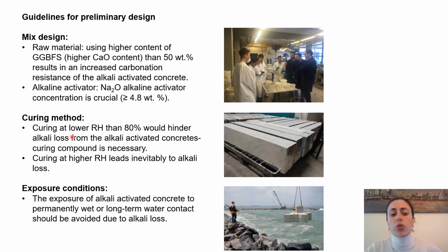Curing methods: curing at lower relative humidity than 80% would hinder alkali loss, or let's say leaching from the alkali activated concrete. So a curing compound is absolutely necessary. And curing at higher relative humidity leads inevitably to alkali loss. This is also something that you can see in detail in my thesis.